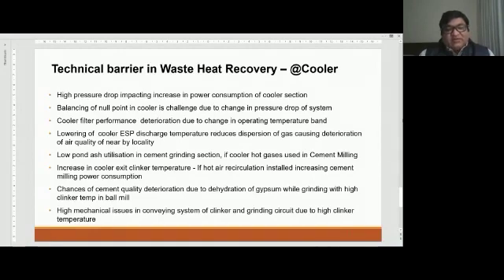Now we understand some of the plants are using pond ash, which has high moisture. So some of the plants were using the cooler gases to dry the pond ash. With the heat of the cooler gases, we can dry it and use it in our cement grinding process. But if you put in this WHR, your heat availability to dry the pond ash or the low quality fly ash, which has the moisture, will become very restricted, and your mill performance as well as your economics can be changed.